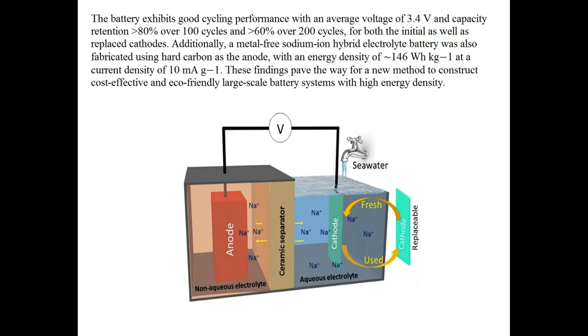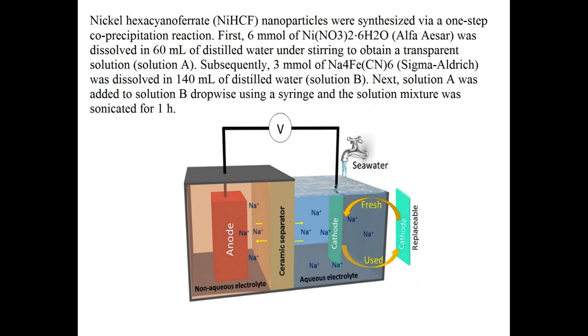Additionally, a metal-free sodium-ion hybrid electrolyte battery was also fabricated using hard carbon as the anode, with an energy density of 146 Wh/kg at a current density of 10 mA/g. These findings pave the way for a new method to construct cost-effective and eco-friendly large-scale battery systems with high energy density. Nickel hexacyanoferrate, NiHCF, nanoparticles were synthesized via a one-step co-precipitation reaction.